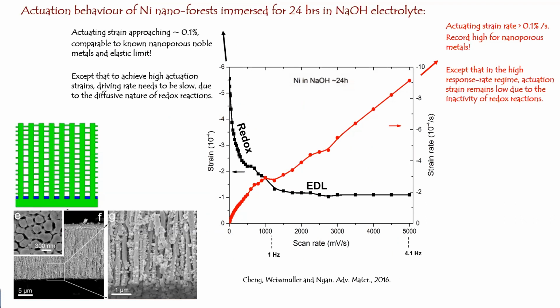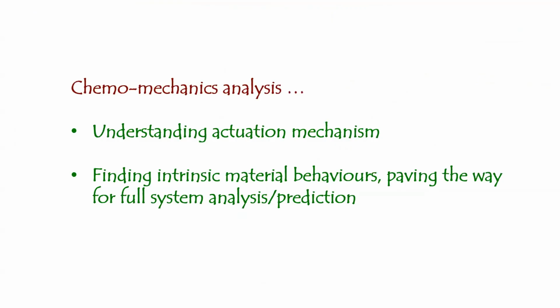When the scan rate is low, you can have the redox happening, and when you do have the redox happening, you can have a big increment in the actuating strain. But when you have a fast scanning rate, the redox cannot happen. You can only have the EDL. So that's quite an interesting material system, which exhibits this dual behavior in electrochemical actuation. And then in what follows, I will walk you through some chemomechanics analysis.